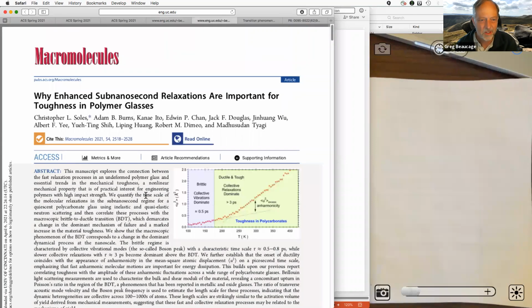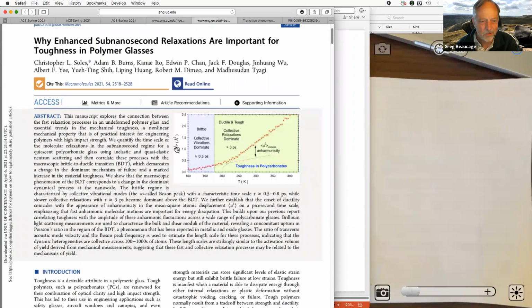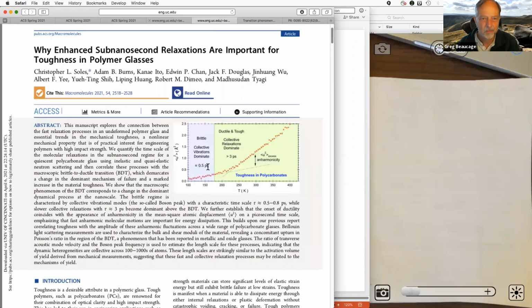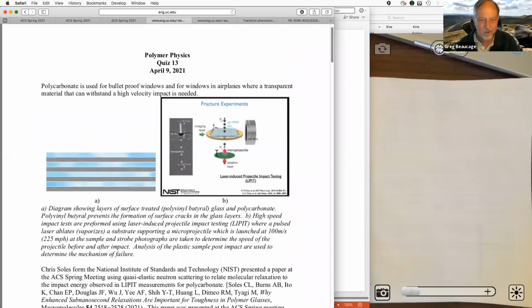Right, so the paper is this paper, and he's showing this mean squared displacement. This is obtained from the broadening of the scattered peak, and then he's plotting that against temperature, and you find there's a transition from brittle behavior to tough behavior. So you can pick out a feature, and that goes along with the behavior that you see in this laser-induced projectile impact testing (LIPIT) kind of measurement.